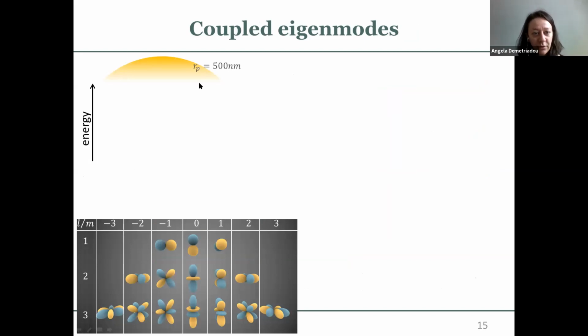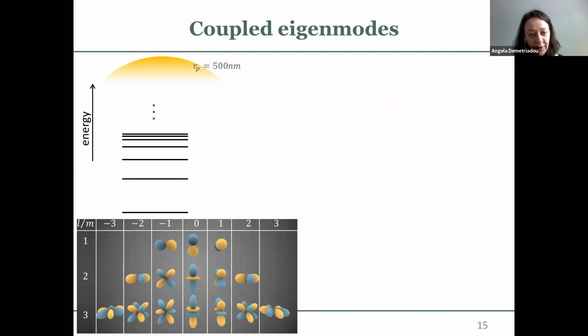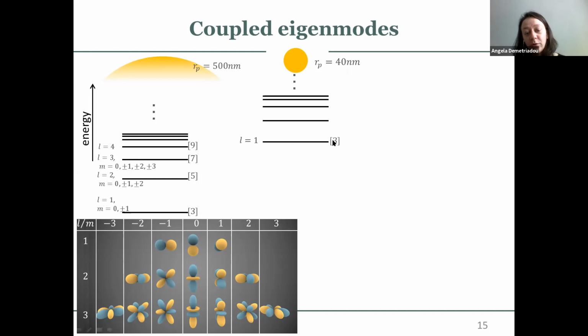So I start with a very, very large spherical nanoparticle, which supports a certain set of discrete modes, right? The first order mode is basically the degeneracy of 3 modes, which are these 3 modes here. The second order mode is a degeneracy of 5 modes. And the reason that you have the degeneracy is that you have a spherical symmetry on your nanoparticle. And the same continues on for the higher order modes. So for L equals 3, the third order mode, you have 7 degenerate modes. And for L equals 4, you have 9, and so on. And if I have a very small nanoparticle with a radius of 40 nanometers, you see a very similar behavior. Again, for the first order mode, 3 modes that are degenerate with each other, which correspond to these 3 spherical harmonics. The second is the 5 modes, which correspond to these 5 spherical harmonics, and for L equals 3, you have 7 degeneracy and so on.